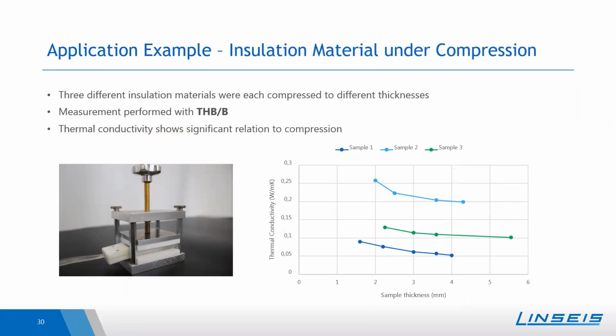Within this slide, also an application example is shown where some soft compressible insulation materials were investigated under different levels of compression. Here, not the pressure was determined, but the sample thickness was controlled using such a manual press. And then the sample thickness was measured. Here also a THB sensor was used, but without the metal frame. And one can clearly see here that the thermal conductivity changes with the sample thickness. So it's also relevant for soft materials to know exactly the measurement conditions to be able to understand the application and the results of the thermal conductivity more in detail.